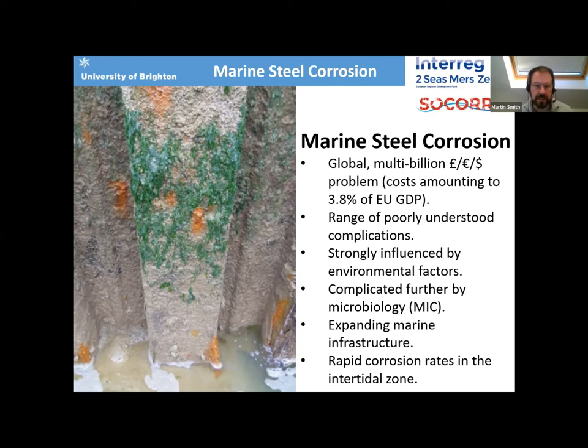These orange blisters, they're evidence of microbially influenced corrosion. Basically, these orange blisters are full of bacteria and they enhance corrosion rates. So this is the problem we've set out to tackle. And it's particularly important at the moment.